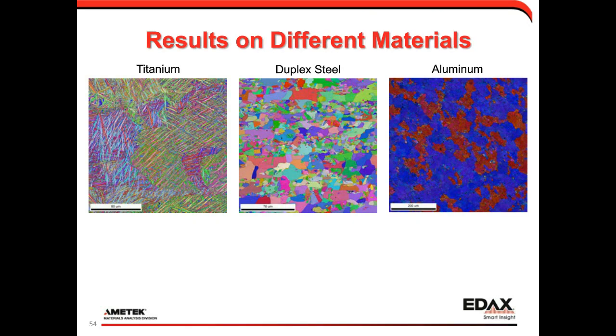So this slide just shows the result of this preparation procedure on a few different materials. That's some titanium there on the left, a duplex steel in the middle, and an aluminum extrusion on the right. So on a range of materials, it generally works pretty well. This is the procedure we use when we look at samples. It's the procedure that Ron Witt uses when he does some of his samples for his lab. And it's one we've converged on through years of doing samples, and it works pretty well.